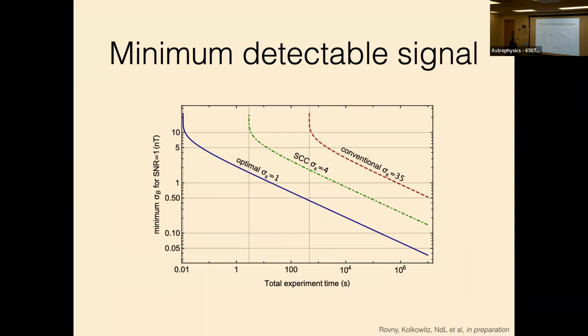Now we can parameterize everything as a minimum magnetic field to achieve a signal to noise ratio of 1 for some total experiment time. Your conventional readout gives you this line here. In order to measure, let's say, a nanotesla, you're talking about something like 10 to the 6 seconds. That's not a fun experiment. Nobody wants to do that. With the spin to charge conversion, you can get this all the way down to something like 10 to the 4 or even 10 to the 3 seconds. This is now not fun territory, but reasonable for a PhD. So people can do this experiment. And then you can write down what the optimal would be if you had a readout noise sigma of 1.